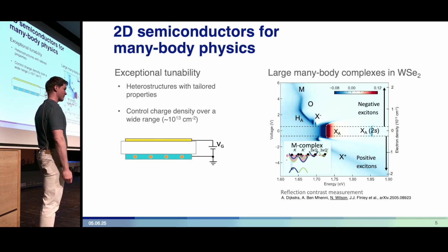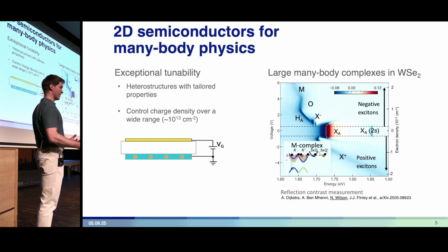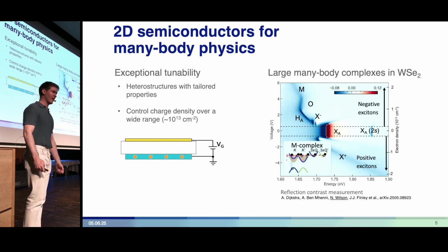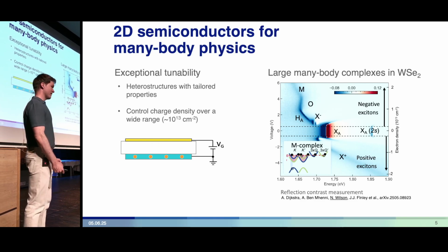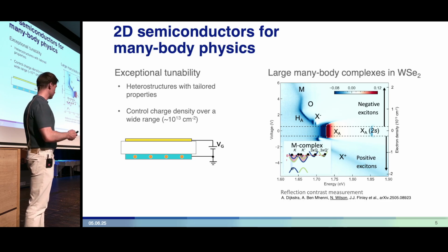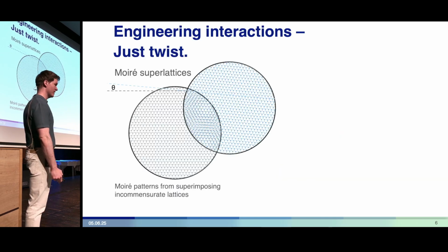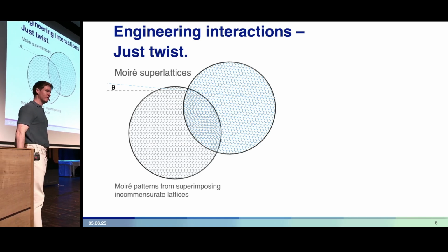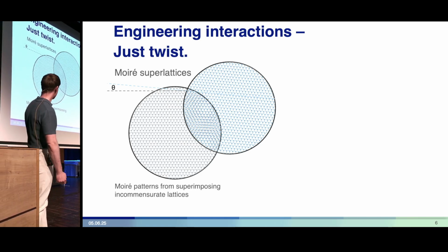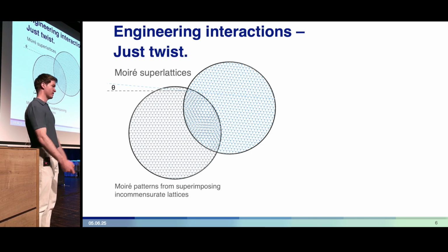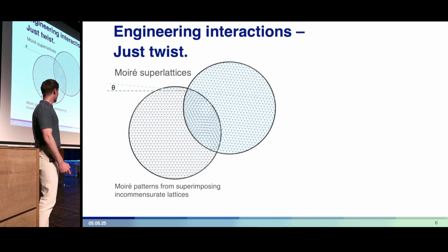But we would really like to see spontaneous ordering of fermions absent some kind of optical excitation. It turns out that interactions between charges that I just inject into the material are themselves usually not strong enough to do this on their own. They need a bit of help. And the push that we need to give them in order to form correlated phases is the introduction of a new periodicity into the system via a Moiré superlattice.